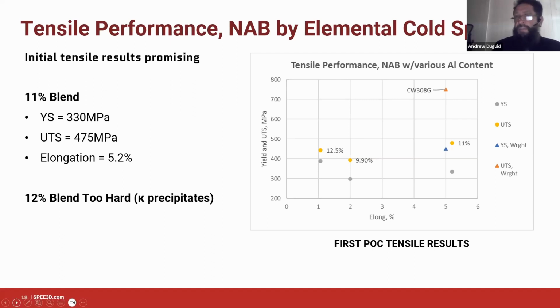So what would we say about that? Well, we actually rely on the aluminium to do some sintering for us in the heat treatment because it liquefies. You can imagine that as we heat the alloy up quite quickly and the aluminium goes above its melting temperature and liquefies, and it helps us to bond together any of the unbonded surface and resolve the porosity.